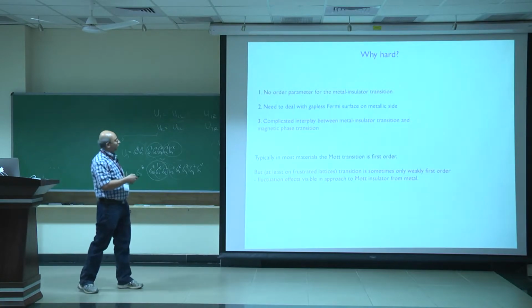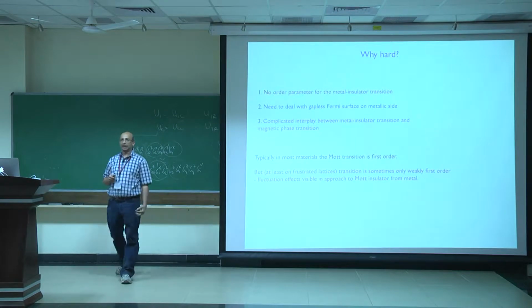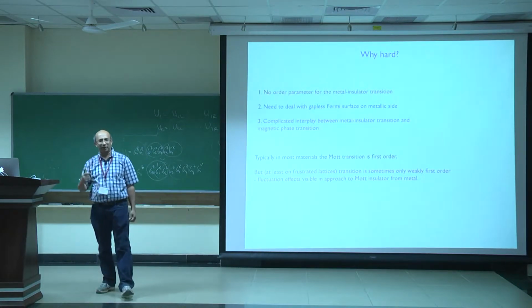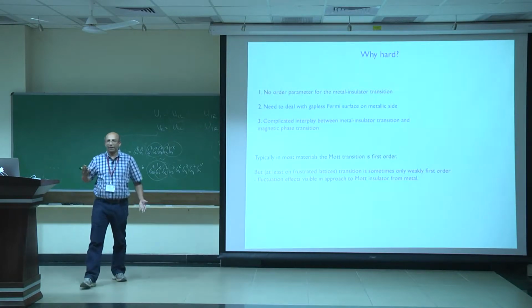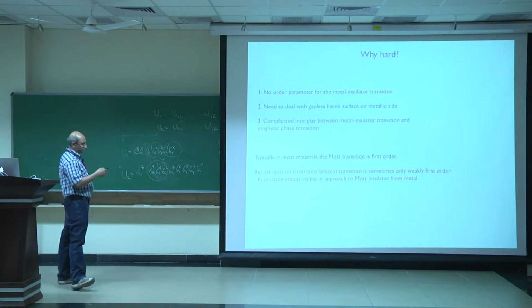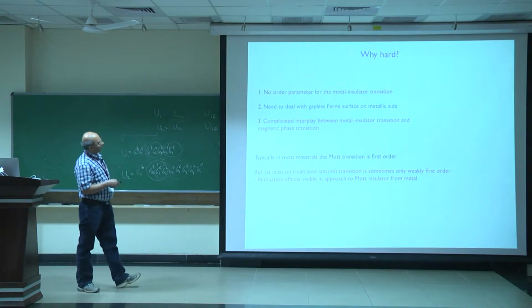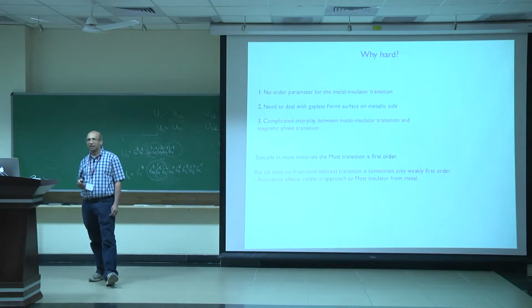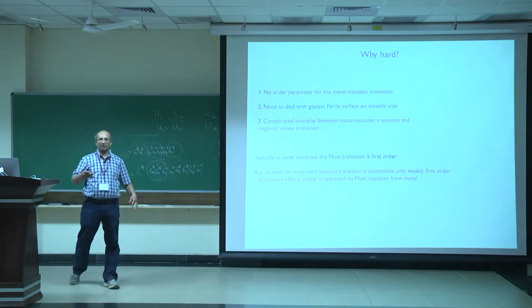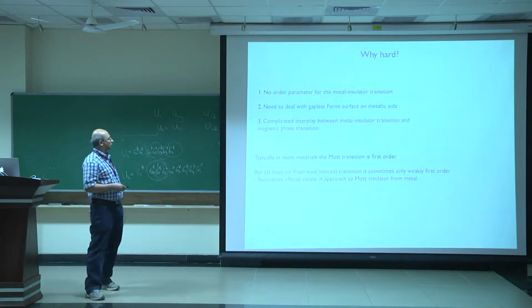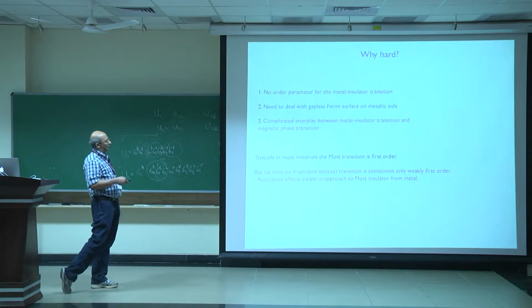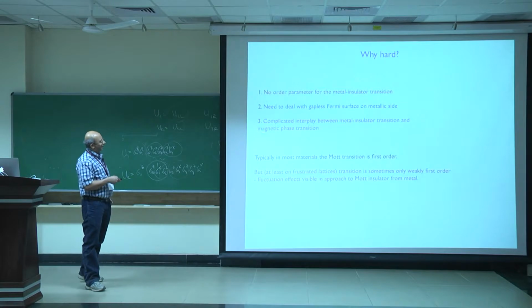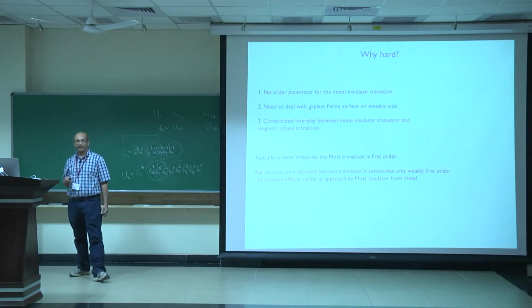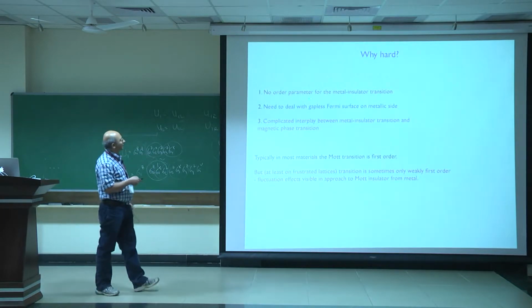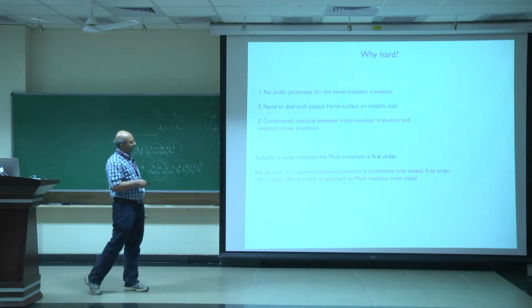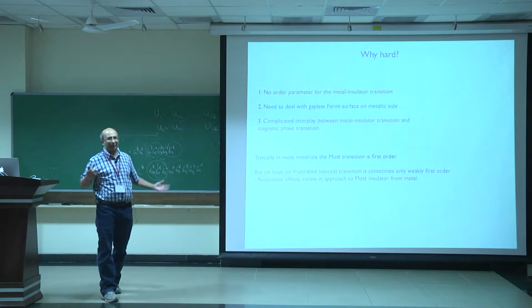So there is no order, but the absence of the order parameter means that some of the standard methodology that we have for discussing phase transitions, which is to focus on long wavelength, long time fluctuations of the order parameter, necessarily, we have to give up on those because there's no order parameter, right? More fundamentally, we have to deal with the existence of the gapless Fermi surface on the metallic side. So it's clearly not just a theory of some fluctuating boson field, but you also have gapless fermions in the problem, and there's a full Fermi surface worth of excitations. Finally, there's a complicated interplay between the fundamental phenomenon of the metal-insulator transition and the other phenomenon of the magnetic phase transition, right? So all of these make life difficult in studying the Mott transition. And furthermore, typically in most materials, the Mott transition is actually first order. And if something is first order, what are you going to say, right?